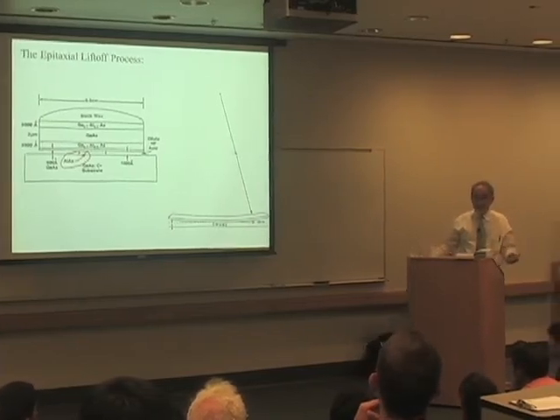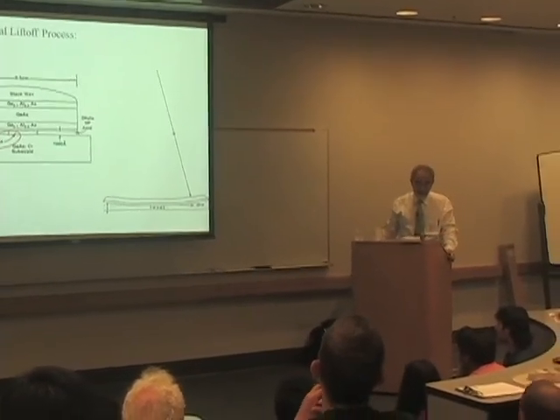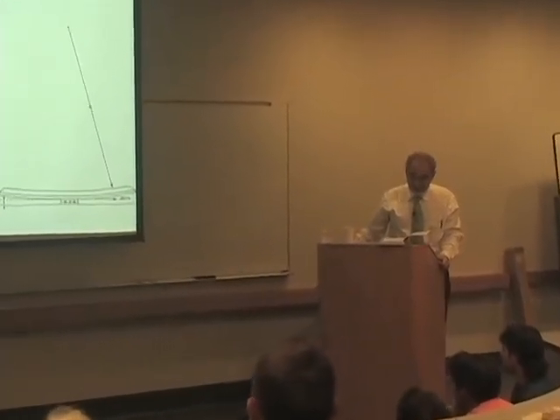And this is a remarkable property in nature. I don't think it has been given a theoretical explanation, but it's used in the epitaxial liftoff process. Think about it: if you have an AlGaAs alloy at 41% aluminum, it's etched by acid. And at 39% aluminum, it is not etched. And the etch selectivity is at least 100 million to 1. This is kind of amazing. There's no theoretical explanation, but it's used in the epitaxial liftoff.